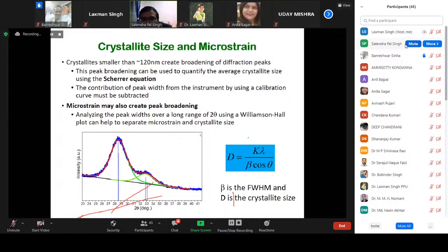The second thing, when people apply the Scherrer equation, they measure the full width at half maxima, and sometimes this peak is not a single peak but also consists of K alpha 2 contributions. So if you have K alpha 2 in the XRD pattern, you have to remove the K alpha 2, then remove the instrumental broadening, and then obtain the full width at half maximum. Only then will your results be correct. Otherwise, you may get false results that will not match the structure obtained from other methods. Some instruments already subtract the K alpha 2, but Rigaku and some other instruments don't remove the K alpha 2 contributions. So you have to remove the K alpha 2 contribution and calibrate your XRD pattern to obtain the instrumental broadening. So using this Scherrer formula is very important, and then you can get the crystallite size. You can compare with TEM micrographs.